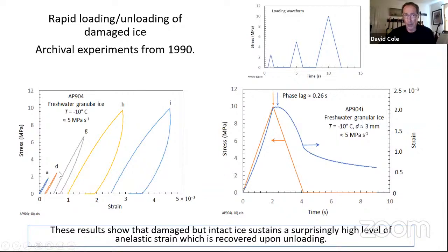The first few at a couple MPa, not much loop area. It looks almost elastic, not quite. What's happening as we go to higher and higher stresses is that we're imparting more and more damage, microstructural damage to the ice, and also loading it up with dislocations, as it turns out. And just prior to failure, eventually there's a high enough stress that you fail the sample in a couple seconds, and it's a very explosive kind of failure.